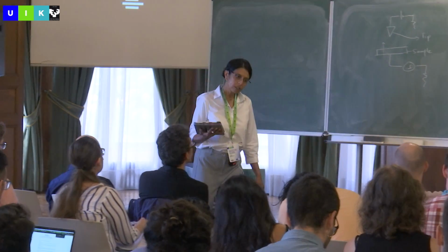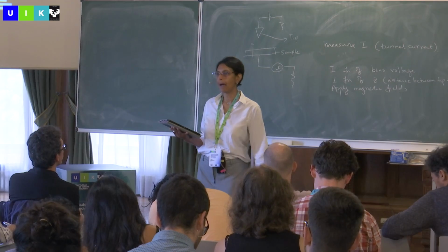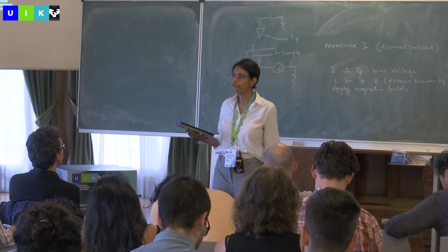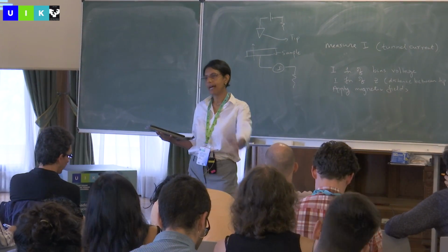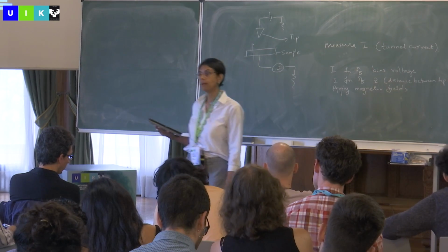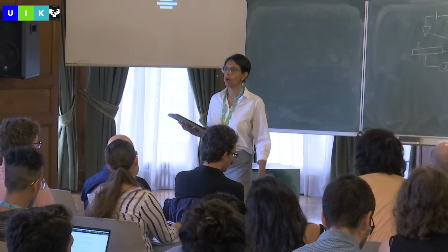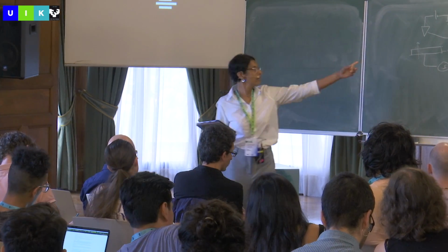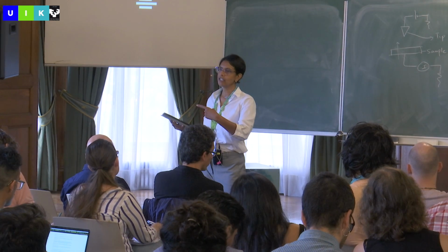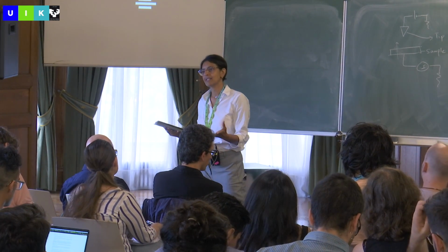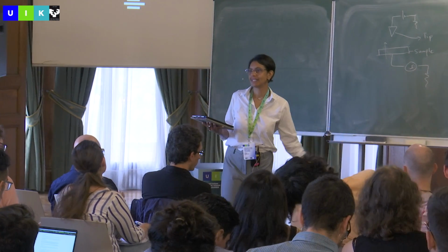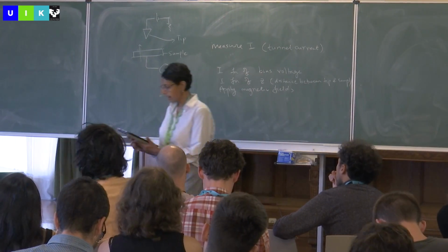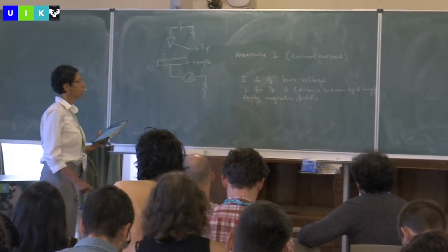We do sometimes use magnetic tips, but the magnetic tips we use are very special. We try to have tips which have very, very small moments. For example, a magnetic tip we might use is chromium. Chromium is antiferromagnetic. So why does that give us any magnetic signal? Because the last atom on the tip has some particular orientation of the spin, and that is what gives us the magnetic signal, but the net magnetism is zero. So those are the kinds of things we use. Thanks. Okay. All right. So this is how STM works.